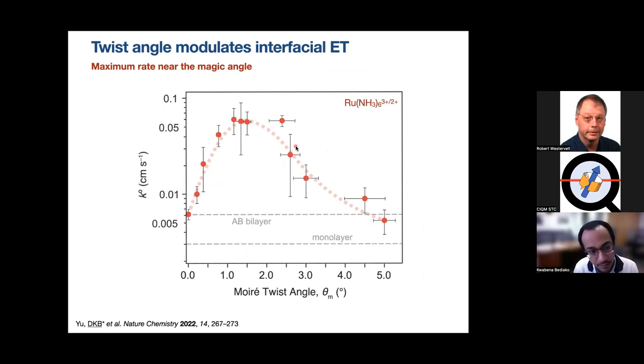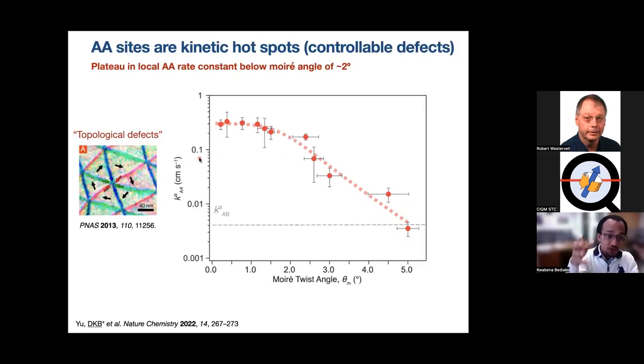Okay, but what are the implications of all of this for interfacial chemistry that I originally motivated all of this with? Well, going back to what we had measured, I showed you that the angle dependence of the electrochemistry follows this trend. What we can do is we can look at the rate constants, which in these cases are ensemble rate constants over the entire moiré superlattice, and we can extract the rate constants at the AA site specifically. And that's because we have this geometric information from 4D STEM. All right. So we can extract the local AA-based rate constants. And what we find is that those are the dominant sites for this electrochemistry. Those are the hotspots. That's where all the electrochemistry, the action, is happening.